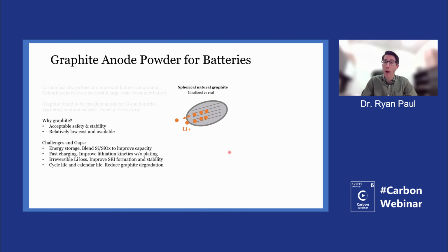So it leads to the question, why graphite? Why, despite graphite not being the sort of the best anode material, why is it the main anode material today? And really, I think number one, it's because there's acceptable safety and stability, because you're working with lithium and different chemistries, and some of them being potentially flammable or explosive and a bit dangerous. Really, for the battery to work, there has to be the acceptable safety and stability, which graphite was eventually shown able to be worked into that. And of course, graphite is relatively low cost and it's available material. So graphite became the sort of a dominant anode material for lithium-ion batteries.